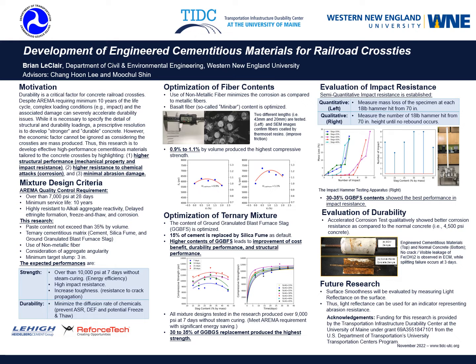On the left, we have mass percent loss. This tracks how much of the concrete sample is still intact after each hammer drop. We do this until at least 20% of the sample is no longer intact.